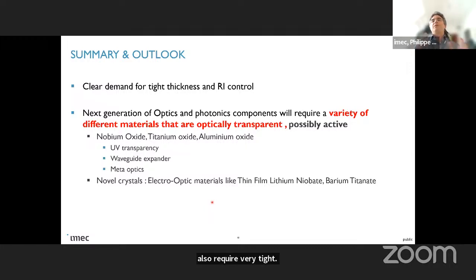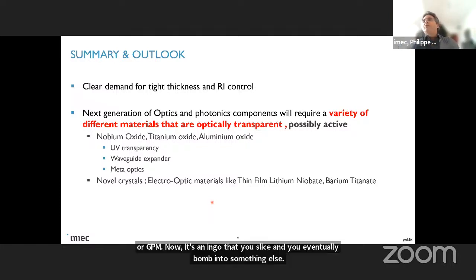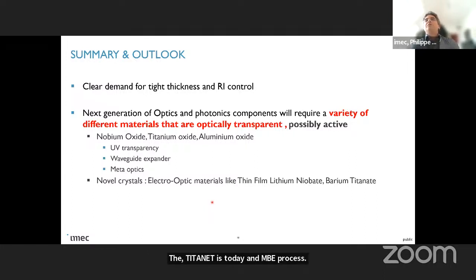The thin film lithium niobate, normally it's an ingot that you slice and you eventually bond onto something else. The barium titanate is today an MBE process, so it's very expensive, but it produces tremendous performance. I think there's plenty of work to be done for this audience as well for these materials.